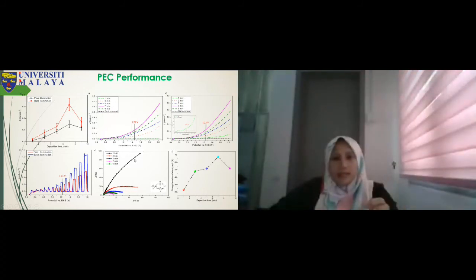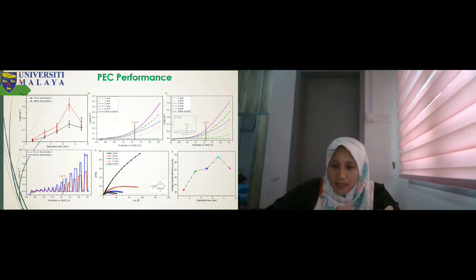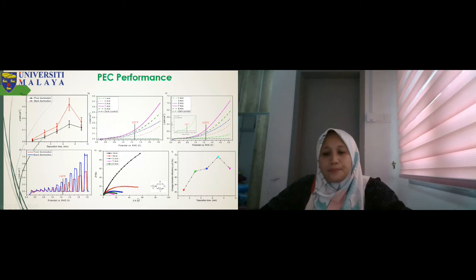At 1 minute, they have a higher charge transfer for this photoanode, for the interfacial charge transfer efficiency. Based on the analysis, it is proof that at 7 minutes we have the higher photocatalytic activity and the higher charge transfer efficiency, around 66.7%.